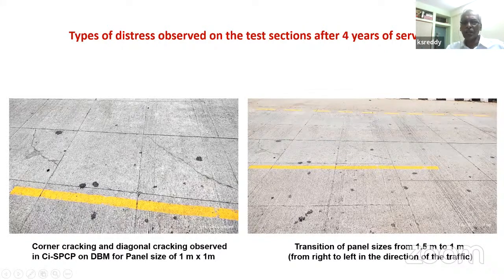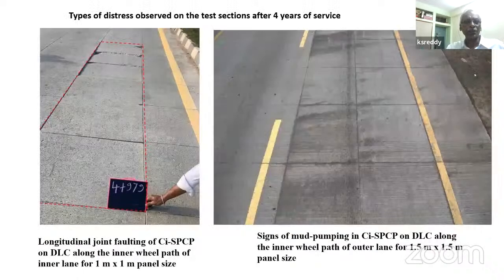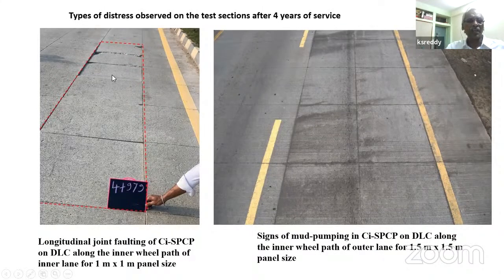But most of the failures have happened because of foundation failures. Let me show you this. For example, this row of panels failed. Once one panel failed, the adjacent panel started failing. This was because of the foundation that we had here. There was water accumulation and erosion of dry lean concrete foundation. Though dry lean concrete is supposed to be a non-erodible foundation, when there is water accumulation and continuous pumping of these panels by heavy loads, there is going to be erosion of all kinds of foundation. So this is one major type of failure that we observed.